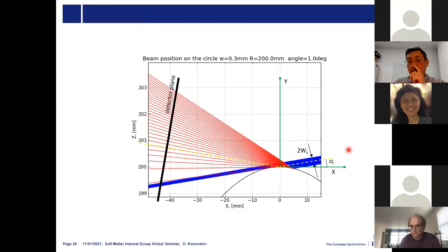So we developed a technique to analyze this data to be able to reconstruct reflectivity data like it would be measured on a flat surface. If we have a curved surface, which is a part of a sphere with some radius, and we have a beam, it's scattered on the surface, so it will spread in some angular fan. And you can see that a little piece of the beam, which we can select here, will scatter somewhere on the detector.